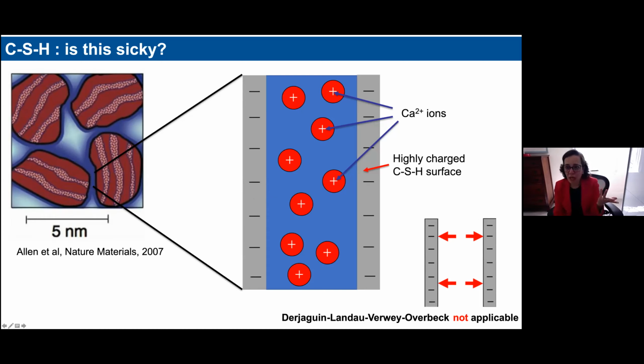But it's not uncommon in colloidal systems. Some of this, for example, can be understood with the DLVO theory. But in this case, this picture really does not apply, because the surfaces, as I said, have quite high negative surface charge, and the counter ions in between are mainly calcium ions, which are divalent. In fact, if you use the DLVO theory to compute the net interaction in this type of system, you basically get only a repulsion. That only repulsion is possible. So what this means is that the cohesive interactions must come from whatever the DLVO does not include. And so they must be the result of strong ion correlation forces that are present in the system due to the high surface charge and the fact that you have divalent or multivalent ions.